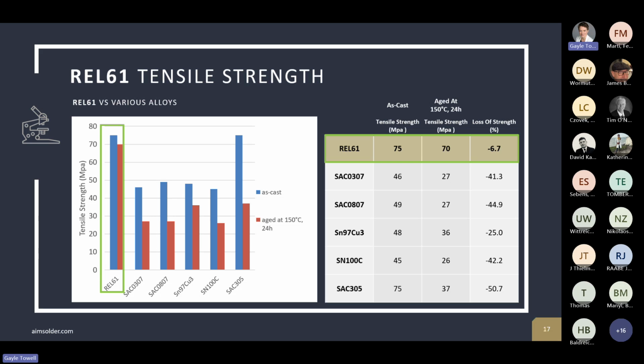This one's my favorite graph. This one shows a really significant difference in tensile strength after aging. So for each of these alloys tested, the blue bar is indicating what its tensile strength was when it's first cast. And the red bar is showing what happens after 24 hours of being aged at 150 Celsius. You'll notice that REL61 starts out high, as does SAC305, but after that thermal aging, SAC305 performance drops off quite a bit, whereas REL61 barely drops at all. And this is true across all of the other alloys as well. Many of the other alloys do not start out as high, but they also see a significant drop in performance. So REL61, again, has that really good thermal aging performance. It starts out strong and it stays strong.